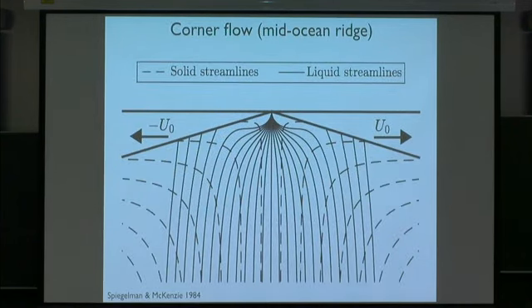And Dan and Mark showed a long time ago that if the parameters are in the right regime, that negative singularity can cause the magma to be focused toward the ridge axis. And so these are streamlines of the magma with the solid in the background. And within some region, which is understood from the calculations, those streamlines are bent towards the ridge axis, and that magma is presumably then erupted as a mid-ocean ridge lava rather than just freezing back into the mantle. So, again, this is a classical result, and ideas have evolved a lot, but it still illustrates a very fundamental part of the problem, which is that the solid flow can set up pressure gradients which the liquid responds to over potentially large length scales.